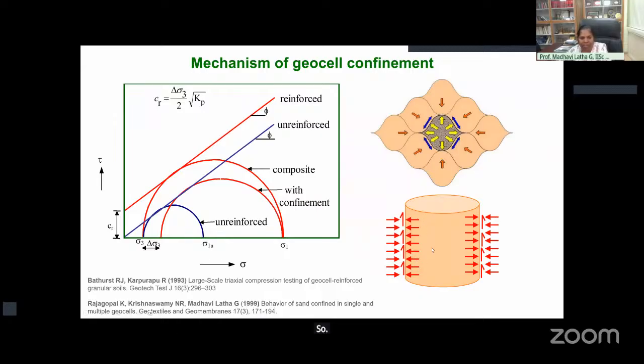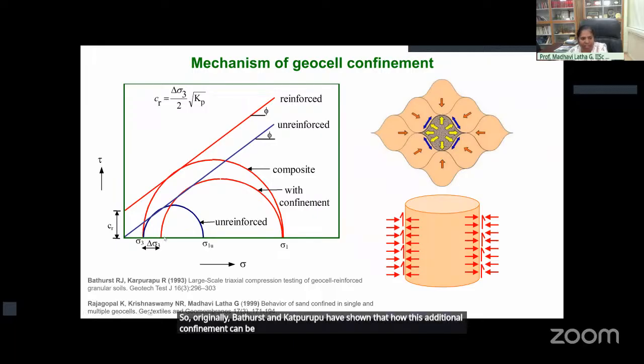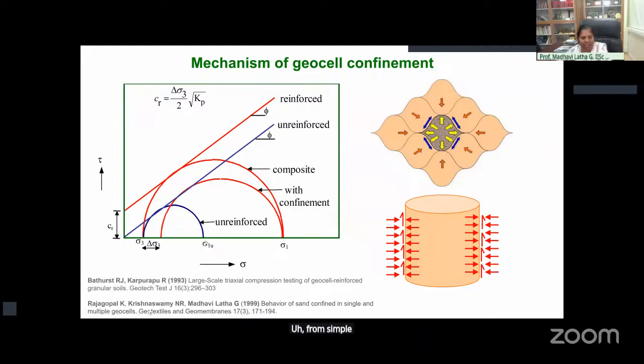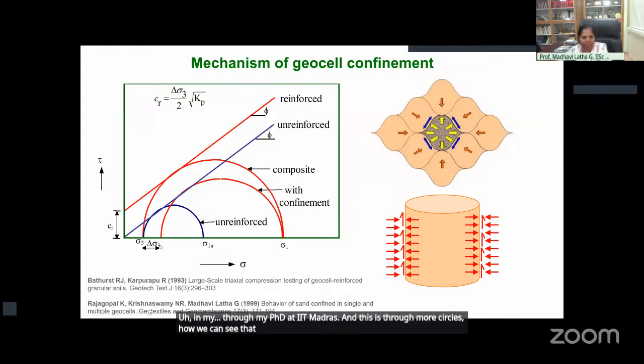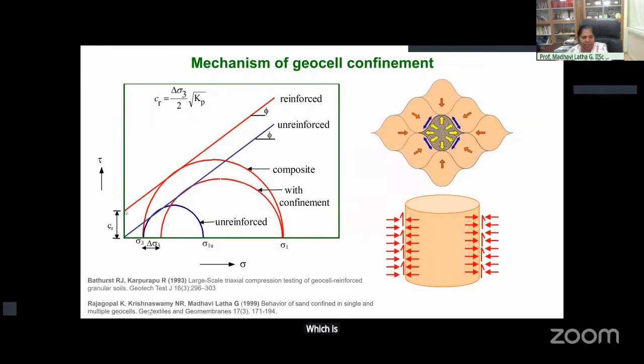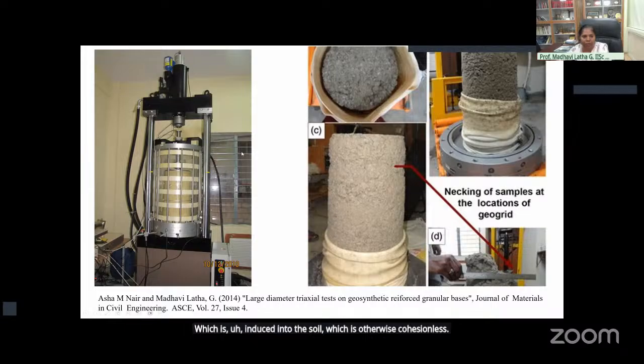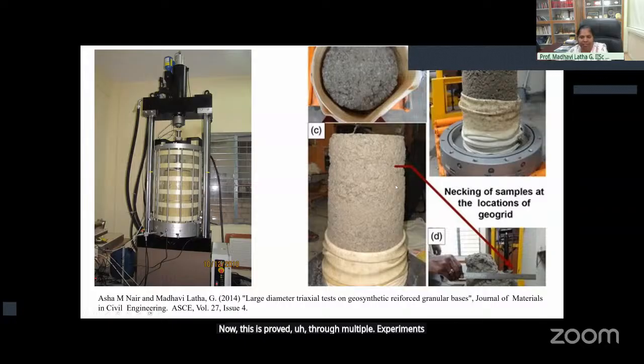So originally Bathurst and Karpurapu have shown how this additional confinement can be quantified from simple Mohr circles, and I have extended this theory to multiple geocells through my PhD at IIT Madras. And this is through Mohr circles how we can see that delta sigma 3, which is the additional confinement due to geocell, can be converted and quantified into the apparent cohesion, which is induced into the soil, which is otherwise cohesionless. Now, this is proved through multiple experiments, element tests and field tests.